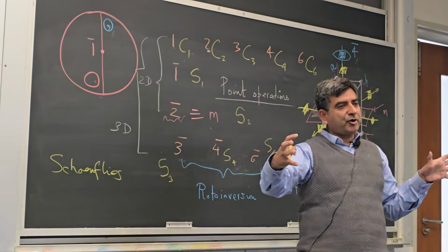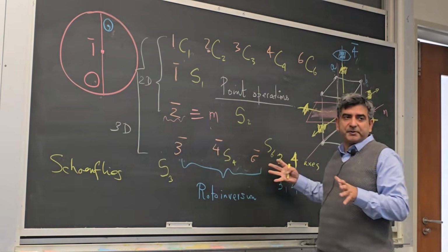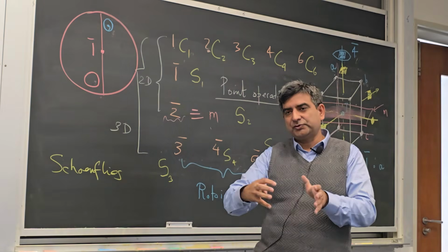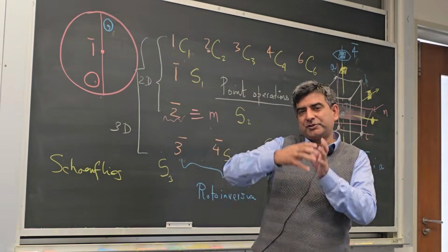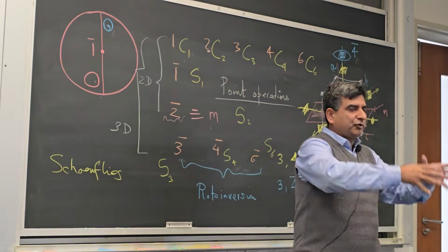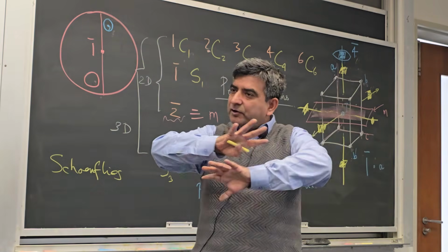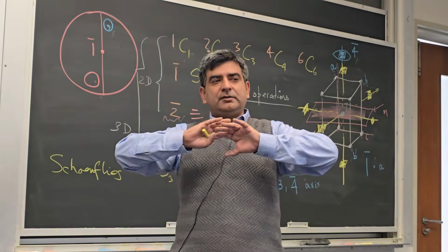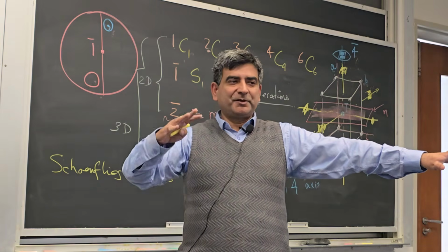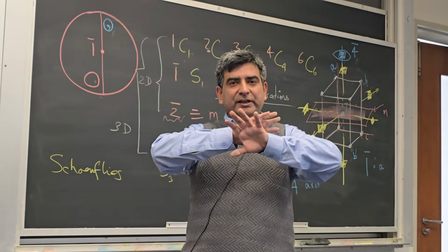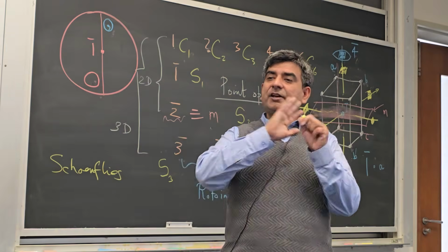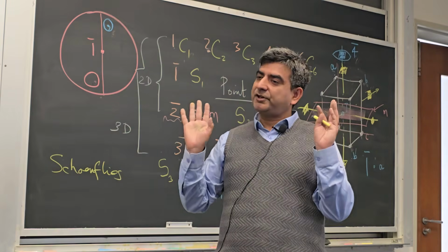So all of these symmetry operations, these 10 different kinds of symmetry operations in 3D, can be lumped together in 32 distinct ways. Those ways correspond to 32 mathematical groups. They are called point groups. Those 32 point groups cover all the possible macroscopic crystal structures. I mean, there are additional groups possible because of translation, but if you ignore all the translations of atoms and only consider point operations, 32 groups exist. They are called the 32 point groups.